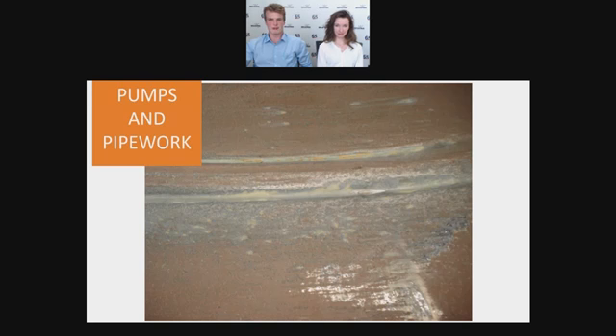So starting with the photo you can see on the slide, we can see damage from entrainment of solids suspended within the flow. If we compound this with corrosion caused by aggressive substances within the flow or the sewage, then we can see erosion corrosion, where the corroded steel is eroded away, therefore exposing fresh steel, which is then exposed to corrosion, and the process then repeats. So we then start to see severe metal loss and ultimately a loss of efficiency and increased operating costs.